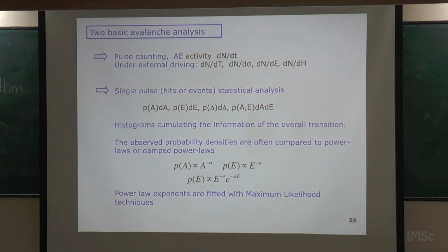So these are the 2 machines that I was saying in the beginning. You can drive like this or like that. Or per magnetic field, if you are in a Barkhausen experiment, the number of events that you get when you change the magnetic field. Because you are driving with a certain constant rate, you transform that into this kind of information. This is one kind of analysis, but this will not discover the distribution of sizes, the distribution of energies. For that, we have to do statistics. We have to make histograms, put all the energies there, and check the distribution. You can do that with the amplitude, the energies, the durations. You can also make 2-dimensional histograms, for instance the distribution of amplitudes and energies simultaneously, etc.